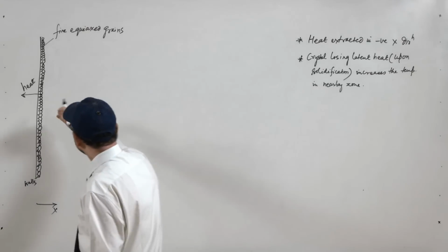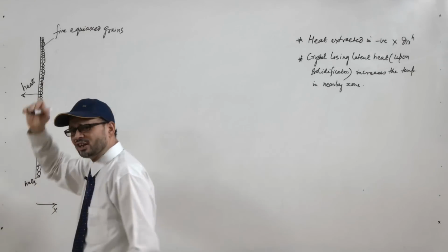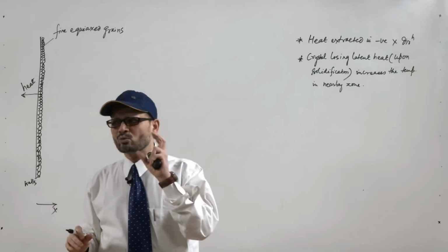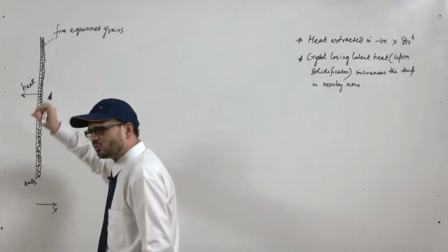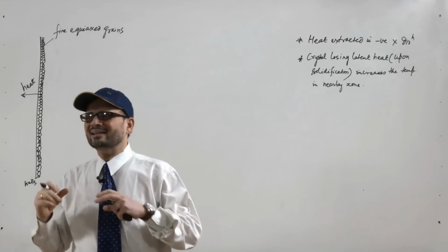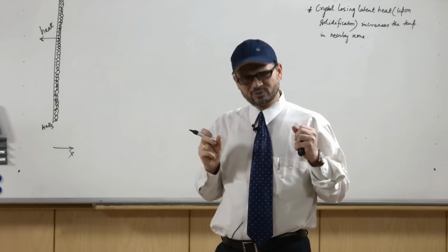Once the temperature of the adjacent liquid is increased, the degree of undercooling experienced by this liquid part becomes less, and that is why nucleation is stopped.